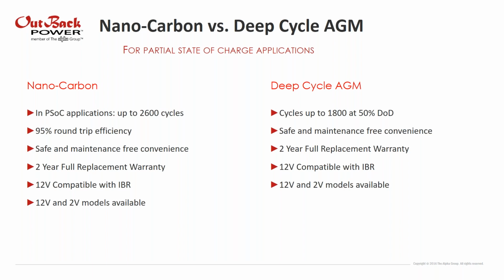However, if you operate a Nano Carbon battery in a 50 to 80% state of charge situation, then that's where you're really going to see that jump in cycle life. It's going to go all the way up to 2,600 cycles, assuming, of course, it does come with caveats, that you're operating at 50 to 80% state of charge and you're doing a full charge, so up to 100%, at least once a month, preferably twice. So without that freshening charge, those cycles are going to go down. But if you do the freshening charge at least once a month and operate between 50 and 80% for the rest of the time, that's where you're really going to see that cycle life improvement.